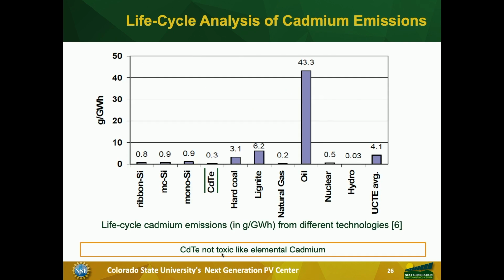And then there is a question of cadmium in the cadmium telluride panel itself. Cadmium is a heavy metal which is not occupationally safe. How much cadmium is emitted into the environment that can get into the human system? And here is the work from Brookhaven National Lab, which talks about how many grams of cadmium is emitted per gigawatt hour, depending on the different technologies of making electricity. And the first thing you notice here is that silicon actually emits more cadmium in the manufacturing process than cadmium telluride itself. And that's because it takes a lot more energy to make silicon panels. And more energy comes from a variety of sources, by burning coal, burning oil, burning whatever. And all of those have, on an average, this amount of cadmium emission.